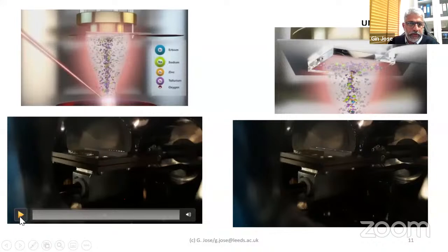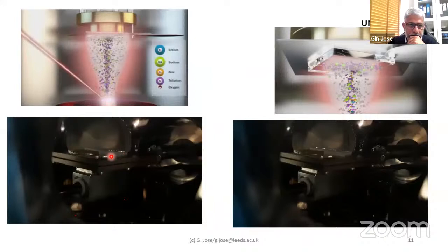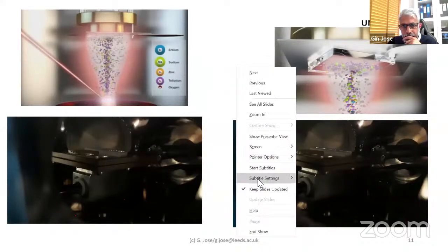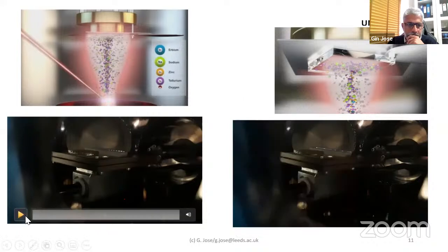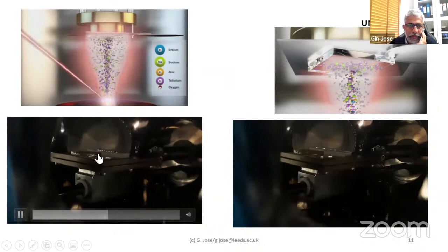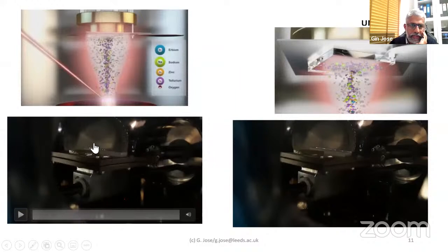So this is a simple video of what happens when the laser is focused and scanned over the surface. That's the kind of target glass I was mentioning. You see that's the glass here, and if I start the laser, you can see that it's being scanned. You see the points where it's mostly getting ablated. The laser is run with a certain repetition rate, or frequency. You scan the laser optically across the target, so that it's uniformly ablated.